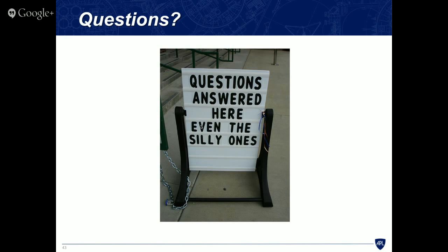One last question. Is there a typical amount of loss due to things that get vaporized when they shouldn't be, or that get lost in the process or stuck in the nozzles? What's the kind of ratio you're talking about? Yeah, so they model that. When we do a laser powder bed process, we do have some evaporation. I couldn't tell you exactly what percentage that is, but when we're done with the part and the part is buried in the powder, and you do an archaeological dig to get your part out, we probably recover about 98 or 99% of that powder.